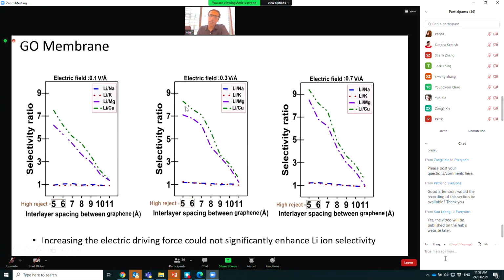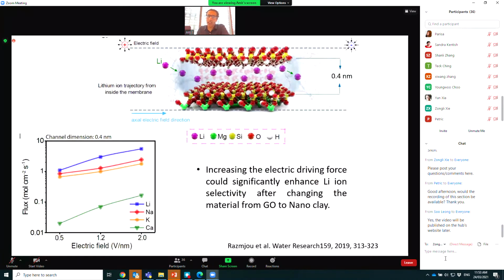And this is another thing: when we increased the voltage across the membrane, we didn't get very significant results for the GO membrane, whereas when we did it for the nanoclay membrane, which still has a 2D structure, increasing the voltage gave us better lithium selectivity and permeability. And that's the very key point: how material contributes to the behavior of ion transport. So all of these parameters have to be considered when designing your membrane. If you choose the right material, right chemistry and right morphology, you will end up with a very nice membrane for ion separation.